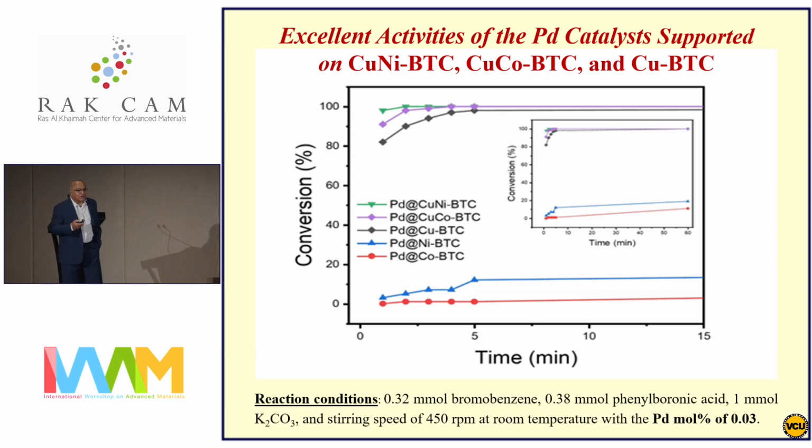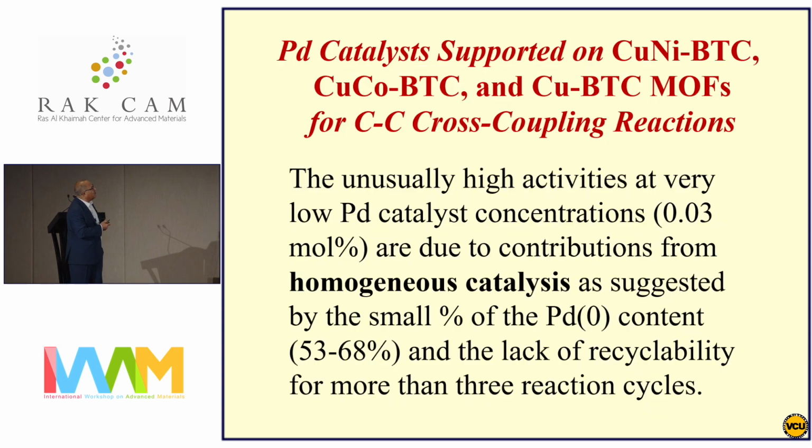So what's going on? It turns out that this catalyst actually cannot be recycled as well as any other catalyst. And it turns out that this catalyst definitely has significant contributions from homogeneous catalysis. So it's not a truly heterogeneous catalyst because of the lack of recyclability of the catalyst. You cannot separate the catalyst and run it over again.